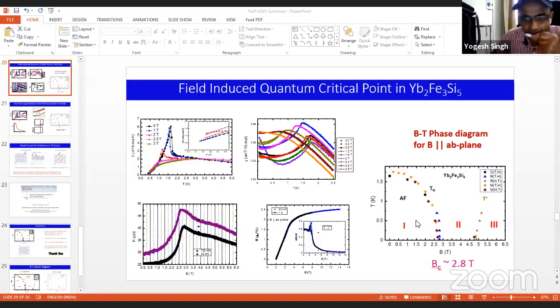Yeah, please have a look at the phase diagram, where you will see that we have tracked the TN using many measurements, including magnetic measurements, which show that the ordering still persists. For example, look at this magnetization versus field, the derivative of the magnetization at 80 milli-K, which is the blue curve. You can see a very sharp peak here. So we have used all kinds of measurements to track the TN, all the way down to 80 millikelvin.